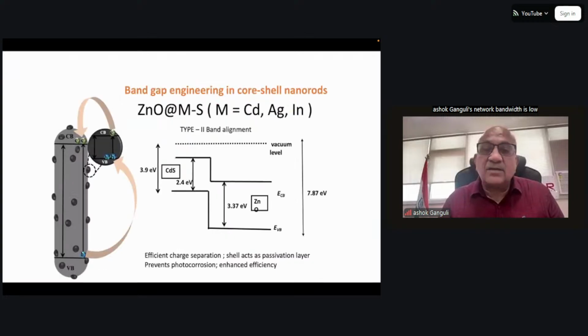So one of the first examples was taking a UV catalyst like zinc oxide and putting cadmium sulfide nanoparticles on top of that. This kind of geometry of two semiconductors is called a type 2 geometry, where the conduction band edge of one semiconductor is above the conduction band edge of the other semiconductor. The valence band edge of one semiconductor is above the valence band of the other semiconductor.